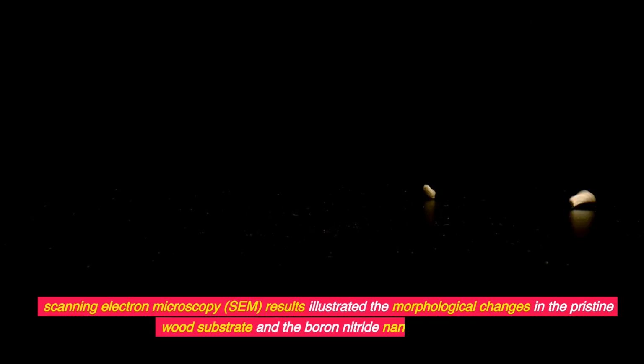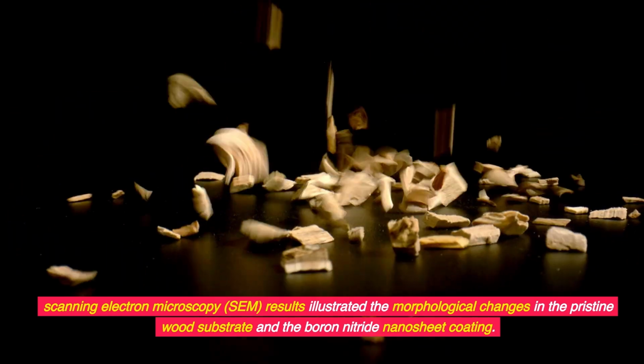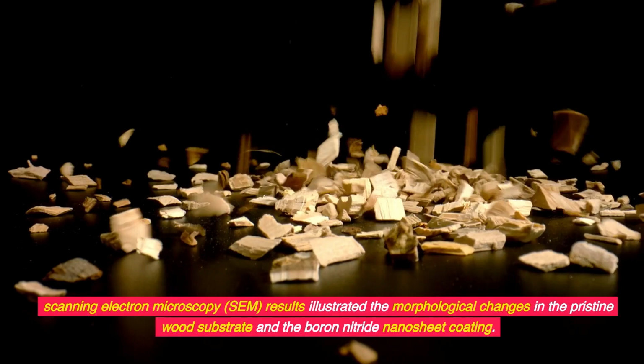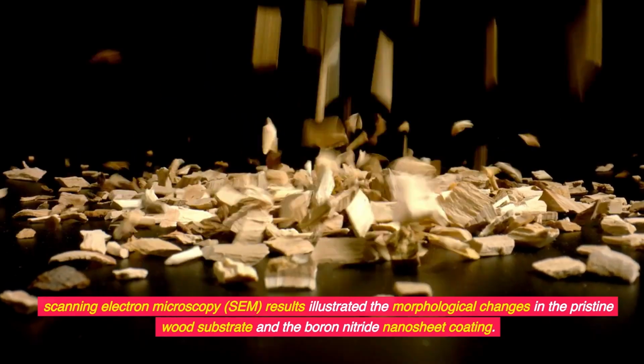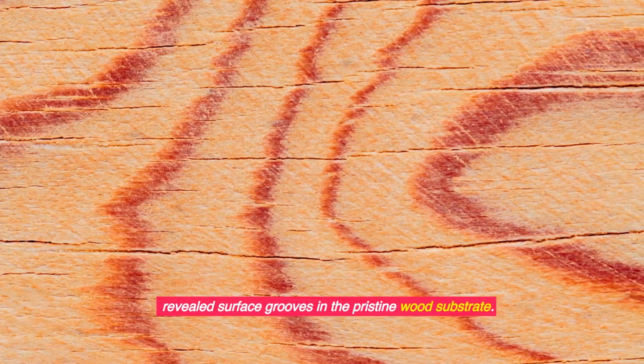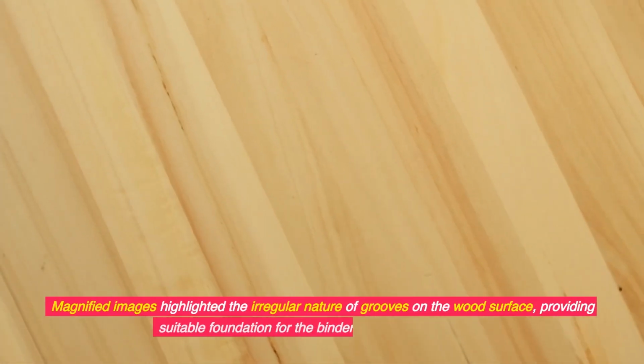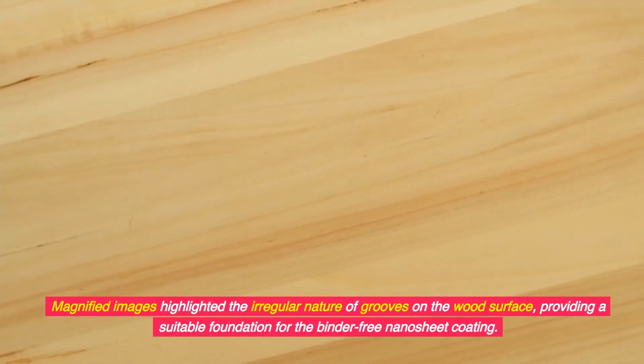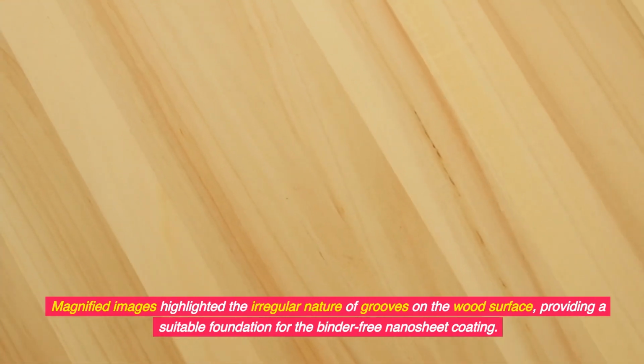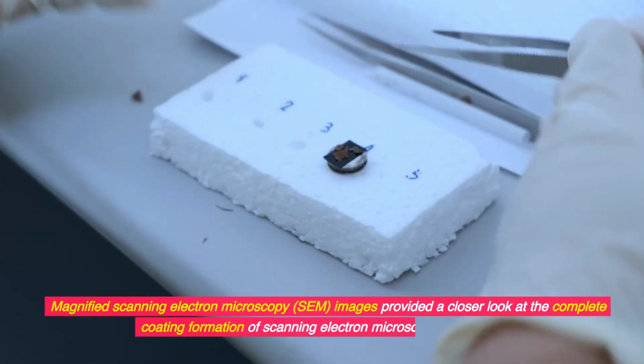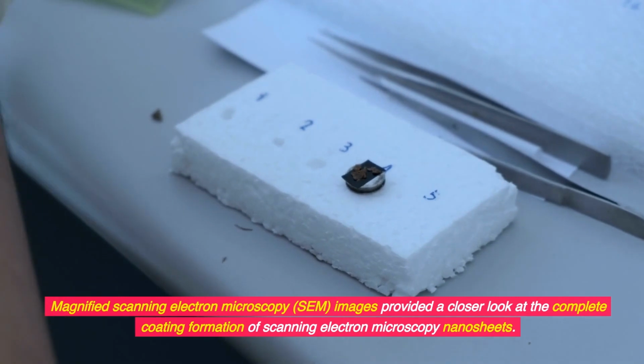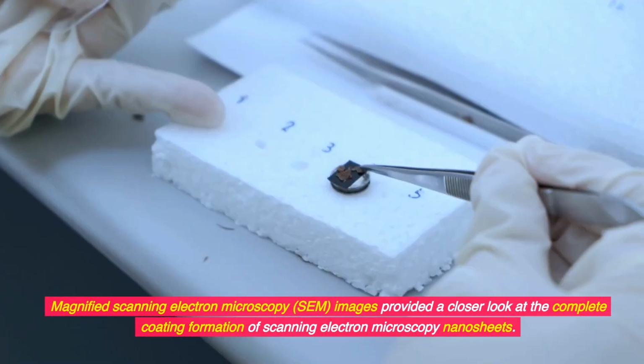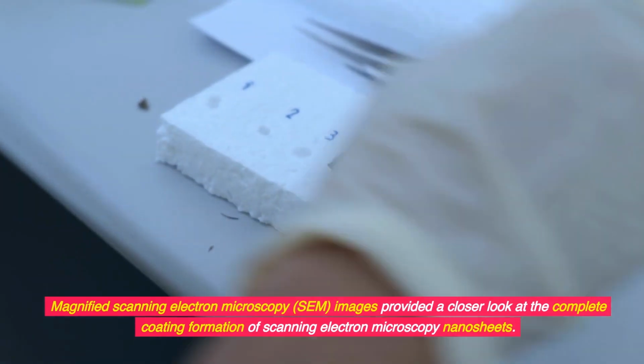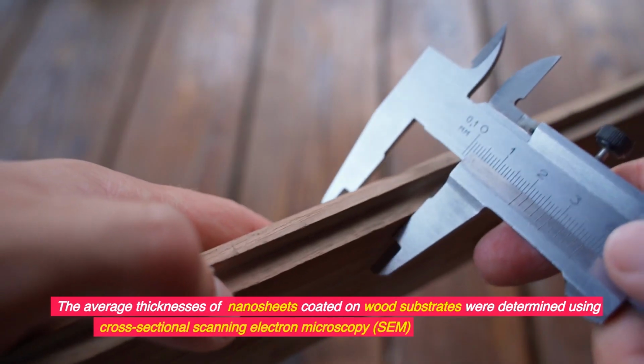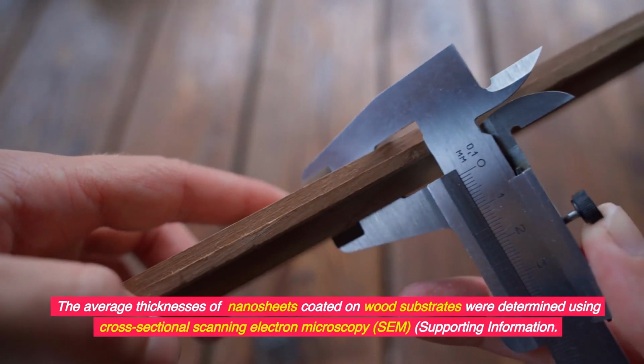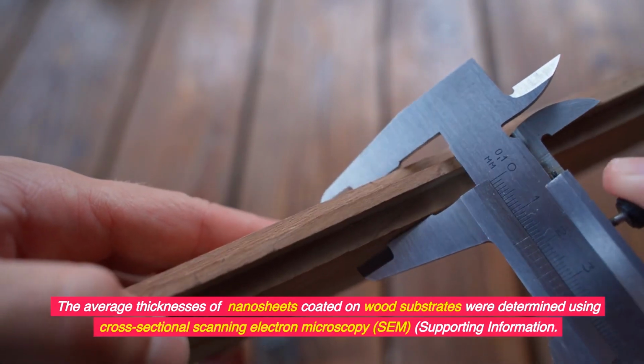Scanning electron microscopy SEM results illustrated the morphological changes in the pristine wood substrate and the boron nitride nanosheet coating. SEM revealed surface grooves in the pristine wood substrate. Magnified images highlighted the irregular nature of grooves on the wood surface, providing a suitable foundation for the binder-free nanosheet coating. Magnified SEM images provided a closer look at the complete coating formation of nanosheets. The average thicknesses of nanosheets coated on wood substrates were determined using cross-sectional scanning electron microscopy (SEM), supporting information.